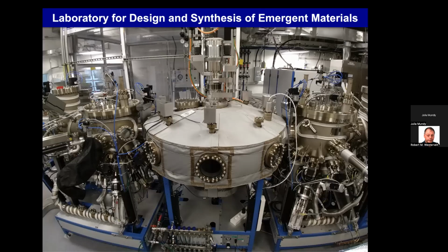Then in those materials, that's when we make that stack of atoms. So then we can repeat the stack many times, but just have 2 atoms in a single sheet. Most of the time when we find the properties vary when you get really thick is because our sample quality goes down over time, because some of our conditions drift a little bit or weren't quite perfect, so the imperfections add up.